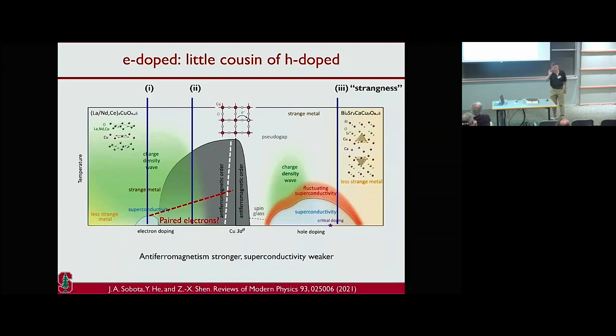I think that's one thing that was a part of this discussion. The reason we have confidence in the P-type system, all those incoherent states in the normal state, is that we are confident this was coming from physics rather than chemistry or disorder of material, because as soon as you cool that thing below TC, it turns into a resolution limited peak. And disorder will not do that. For the same reason, this observation allows me to say I know those are states that really matter for superconductivity.